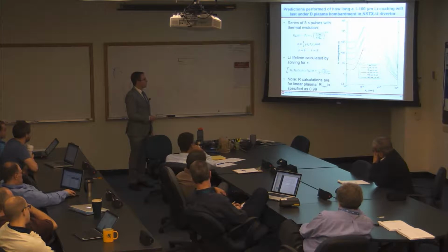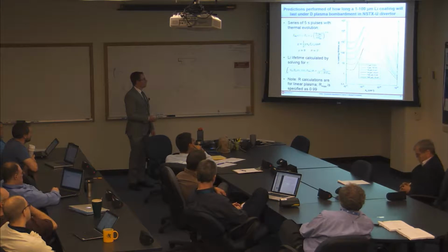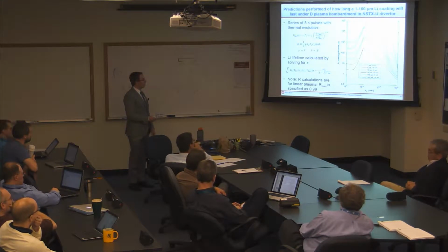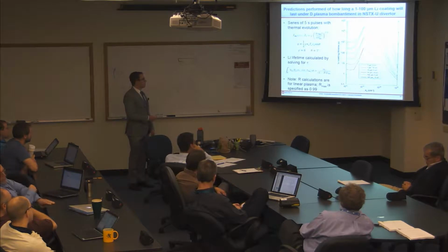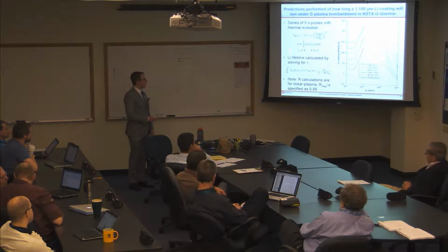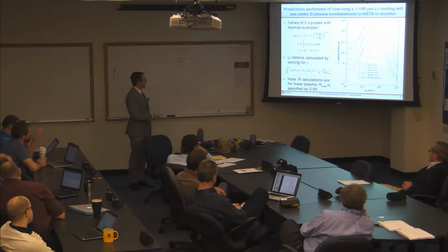And so you modeled the thermal evolution of this layer, just basically using the thermal properties of molybdenum. It's the semi-infinite limit of the thermal diffusion equation. And then for the heat flux, I use this formula from Stangeby, which is the heat flux is 1/2 gamma n_e c_s sin theta. Gamma is the sheath heat flux transmission coefficient, which was assumed to be equal to 8. Theta is the field line incidence angle, for which I used 3 degrees.